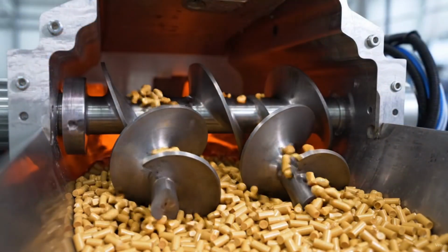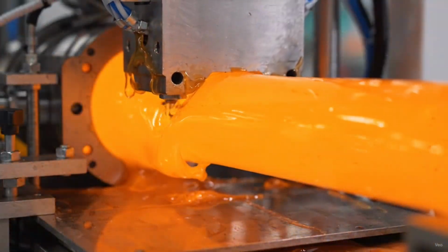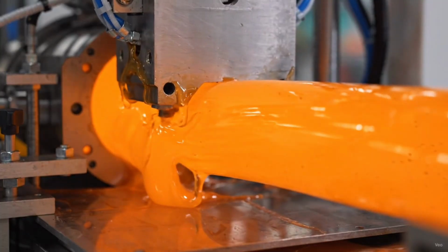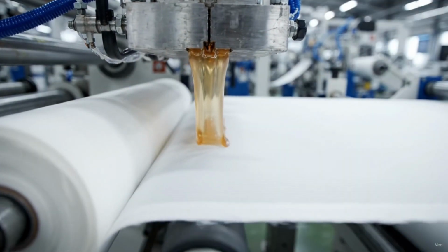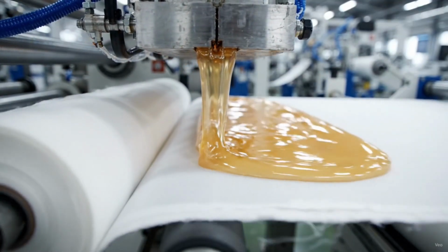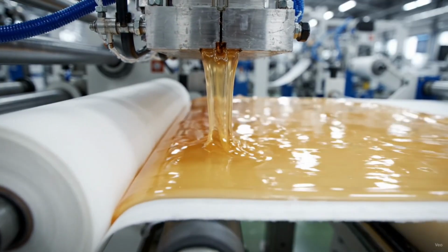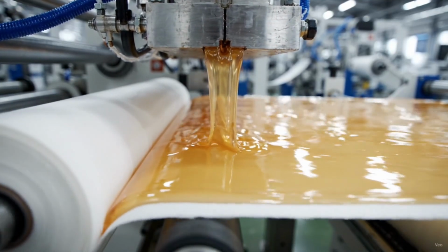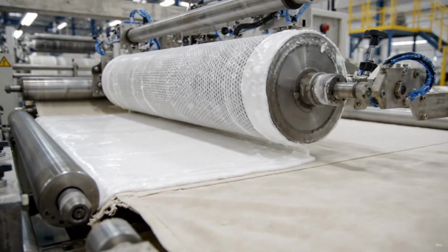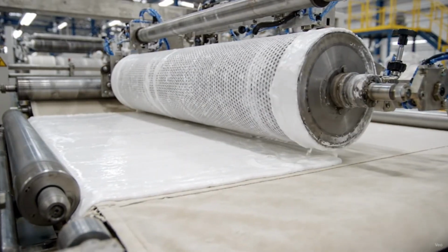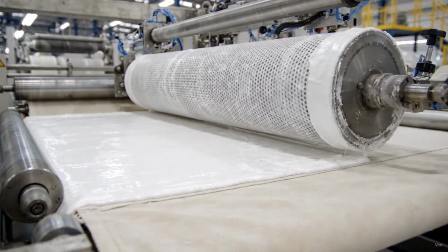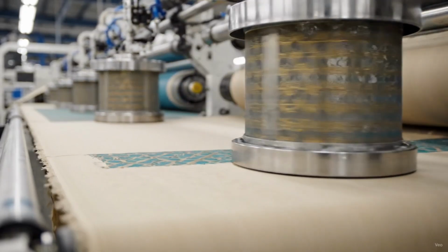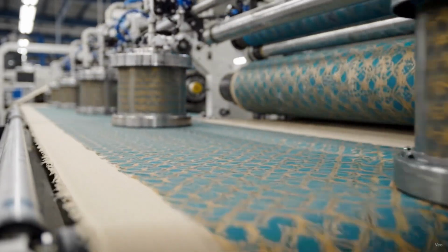Hot melt extrusion begins by melting thermoplastic granules inside an extruder. The molten polymer is applied through a slot die for precise coating control. Rotary screen coating pushes coating material through perforated cylindrical screens. This method enables patterned application and excellent coating consistency.